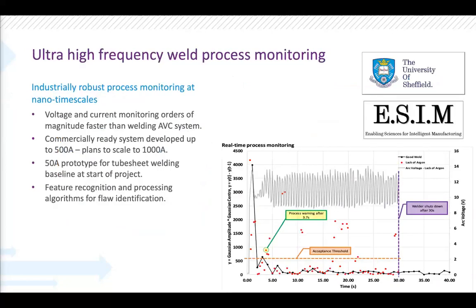So there was a lot of development and work done within these work packages, so I'm only going to touch on a few of the footnotes. The concept behind the process monitoring for the power is that there is already a power monitoring system within the control system for the welding power source, and this is to control the distance between the weld tip and the weld pool. So it's called arc voltage control. This maintains a constant voltage by adjusting the distance of the arc.